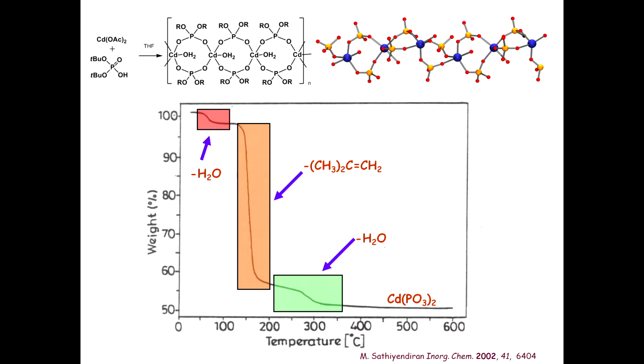And you see this kind of temperature weight loss, which is almost parallel to the y-axis, amounting to about 50% of the weight, which is the loss of the tertiary butyl group as butene. This produces P-OH on the surface, which goes on to self-condense and make this. What is important to note here is that the formation of metal phosphate material in nanocrystalline form happens at temperatures as low as 300 degrees centigrade, and there is no impurity of any kind, because this is a single crystalline polymer, so you have 100% pure compound in your flask.